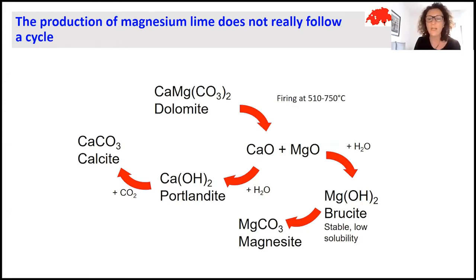By firing this material, I will obtain two different components of the mortar. One part is the magnesium, for which I will have the magnesium oxide, and by slaking, the magnesium hydroxide, which is a mineral called brucite, which is very stable and has a low solubility. And this causes the carbonation of this type of mortar to be very long. So it can take also longer times.